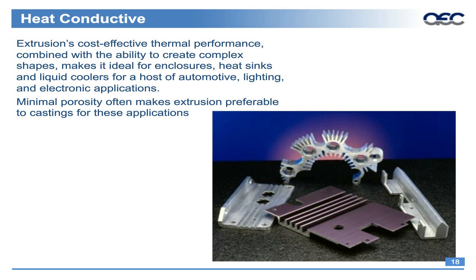But one other important attribute of extrusion itself is it's a forging operation. So when you compare forging operations to something like casting, you'll actually see much less porosity in a forging than you would in a casting. So in a heat sink application or a conductor application, porosity is a very important item in controlling the efficiency of that particular unit. So typically, just in switching from a casting to an extrusion, you will gain something like 5 to 8% efficiency just in switching types of production methods.